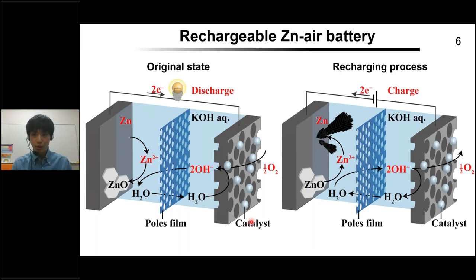However, zinc-air batteries are still used only as non-rechargeable batteries. The difference between rechargeable and non-rechargeable batteries is classified according to whether the charging reaction restores the battery to the original pre-discharge state. In ideal rechargeable batteries, it is expected that the opposite electrochemical reaction will progress during charging and discharging. On the other hand, non-rechargeable batteries cannot be completely restored due to many side reactions. Especially in zinc-air batteries, we found electrolysis as a more major reaction. In addition, various issues remain in the charging process of zinc-air batteries.